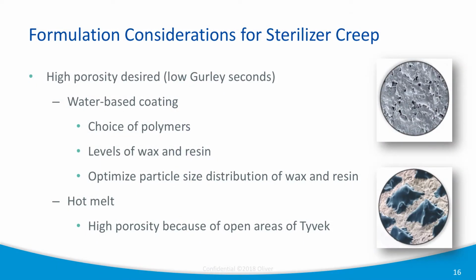So first of all, you wanted to get higher porosity, and just to be clear, there's a test called the Gurley test where the lower you get in that test, the shorter the time to force the gas through, it means higher porosity. So that's what you want to get. For water-based coating, some things that are important are the choice of the polymers. Obviously for porosity, you don't want to have a film former, so you need to maintain some pores in the coating, so that drives your choice of polymers.